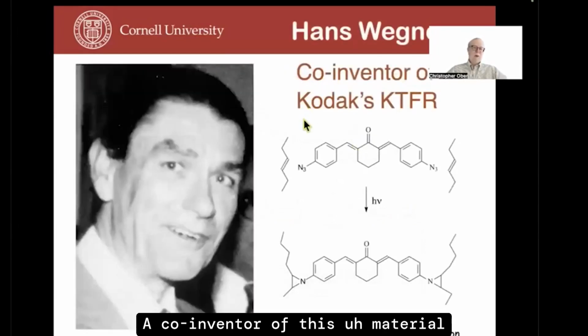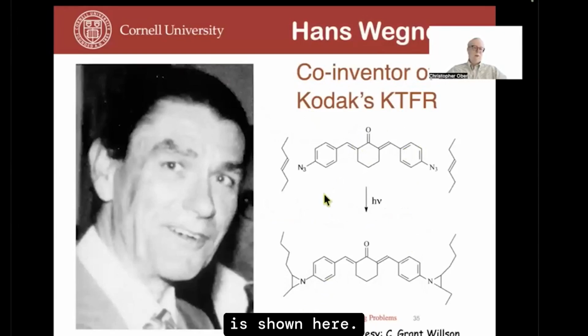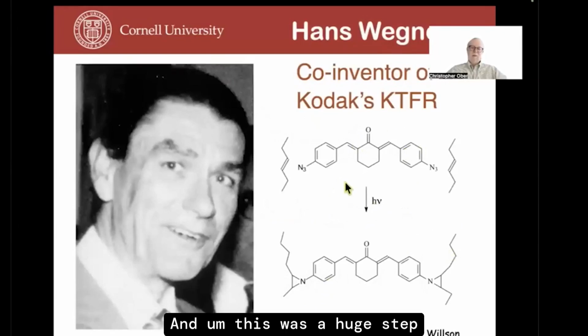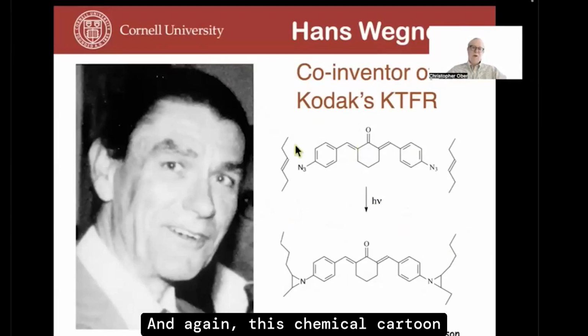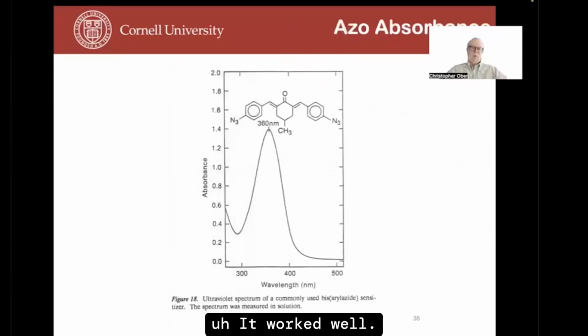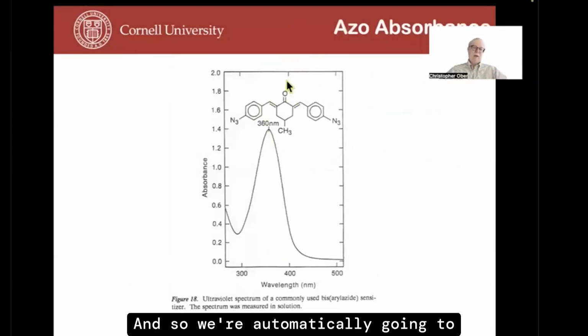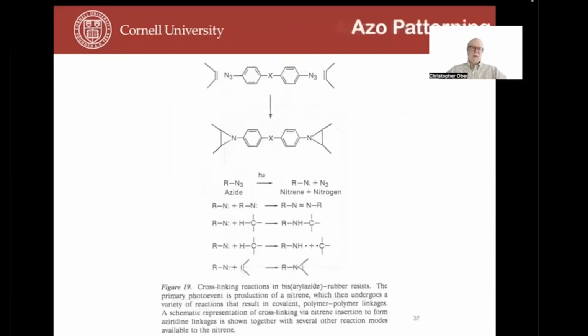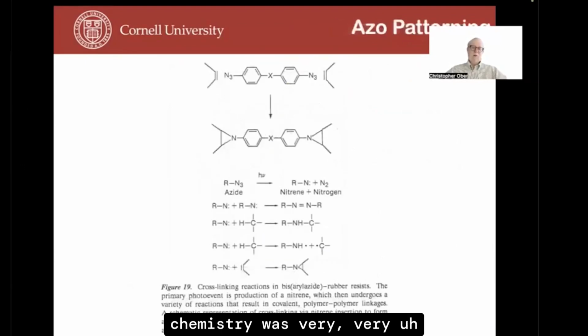And so the co-inventor of this material is shown here. And this was a huge step forward, both for lithography and for the semiconductor industry. And again, this chemical cartoon shows the nitrogen group going after the double bond on UV exposure and cross-linking the material. It worked well at around 360 nanometers. That's the maximum absorption of this particular photoactive compound. And so we were automatically going to the shorter UV wavelengths and driving down minimum feature size. And again, this sort of chemistry was very, very effective and worked well.